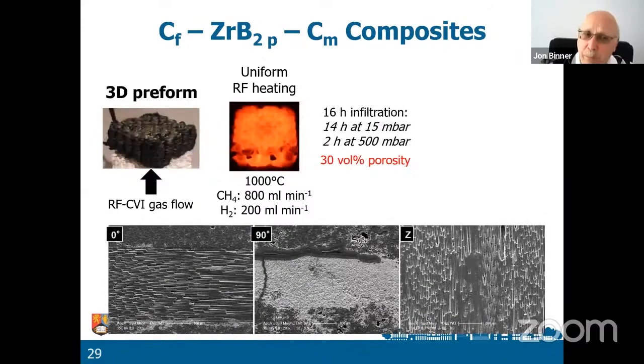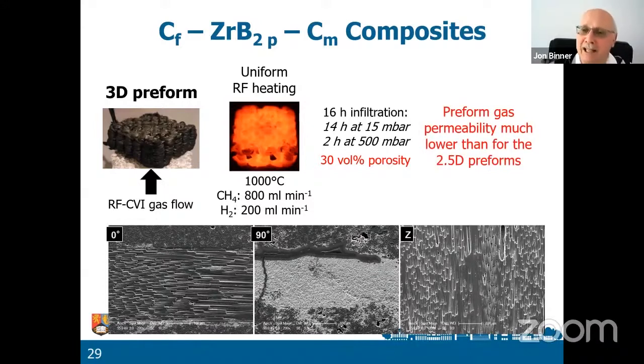With 3D preforms, it's a little different. 3D is slower. After 16 hours of infiltration, we still have 30% porosity. It's only 70% dense. The reason for that is that the gas permeability for the 3D preforms is much lower than for the 2.5D preforms.